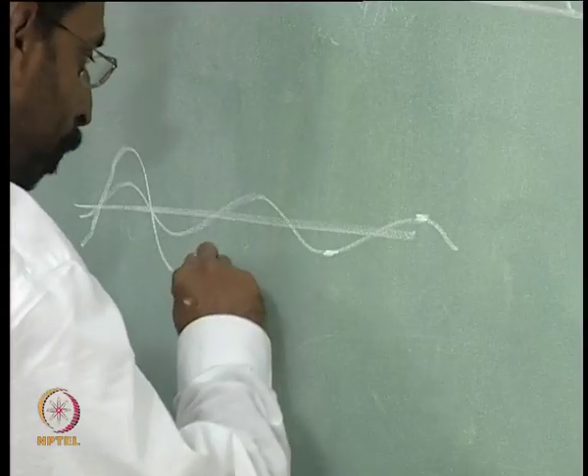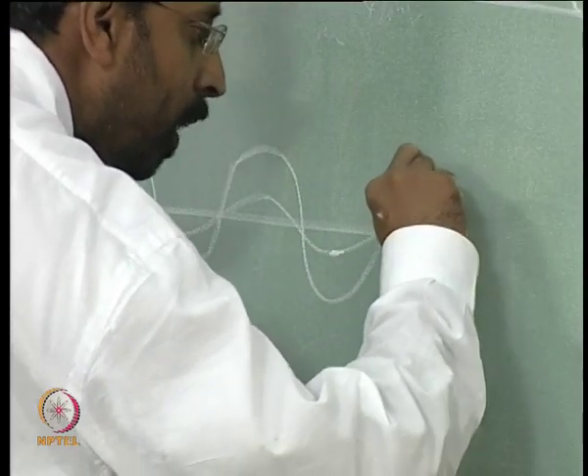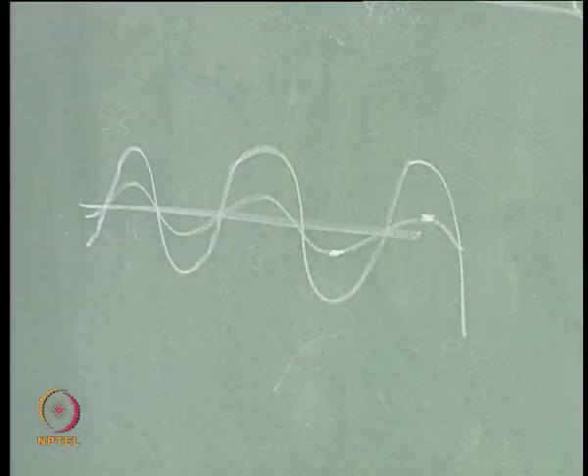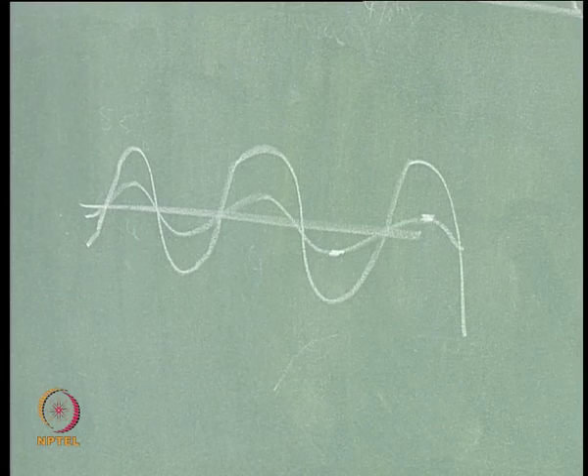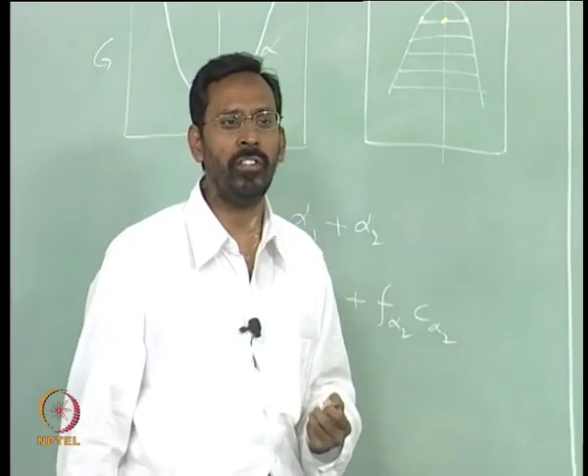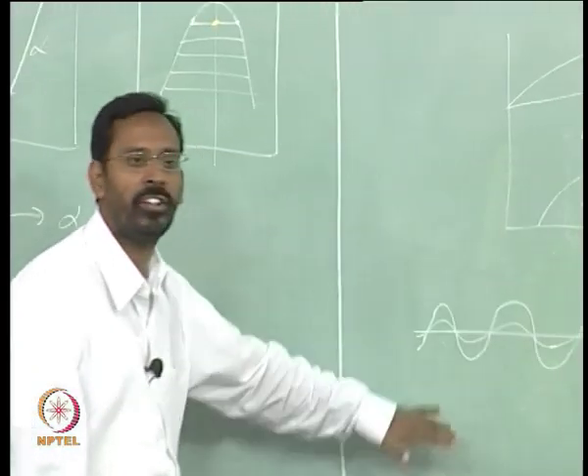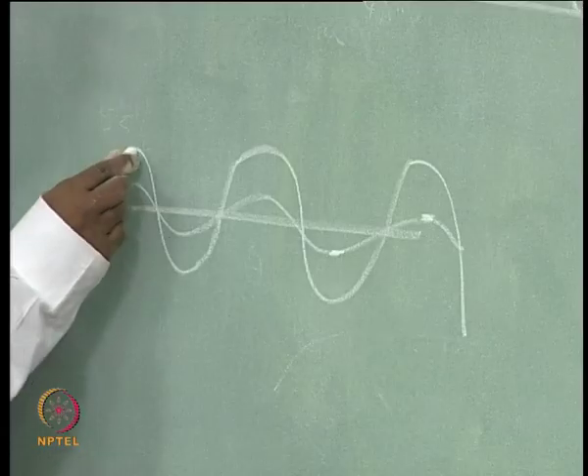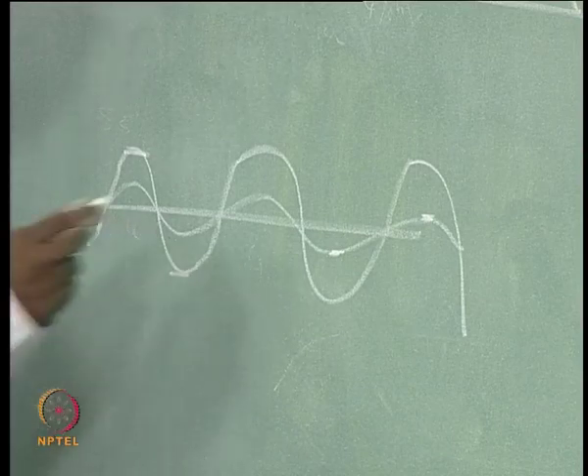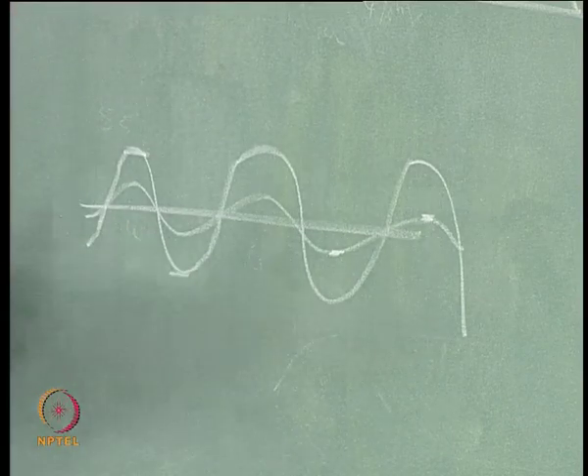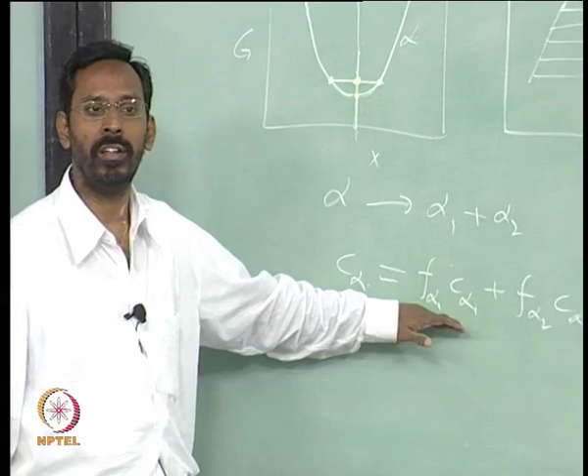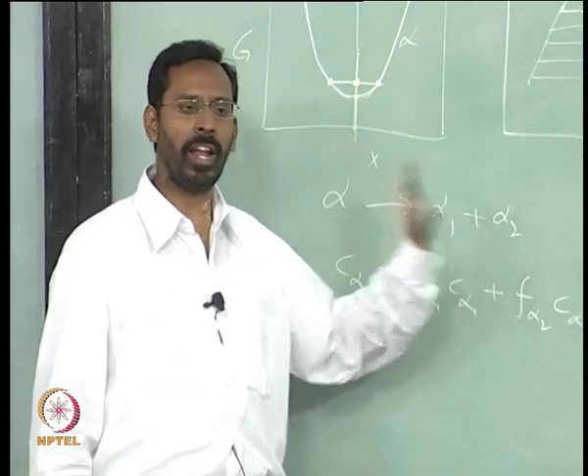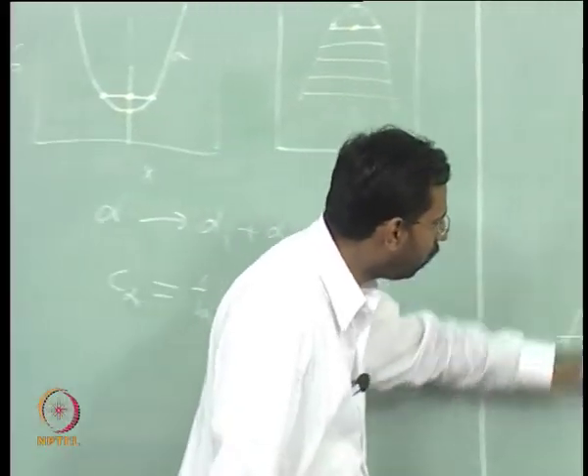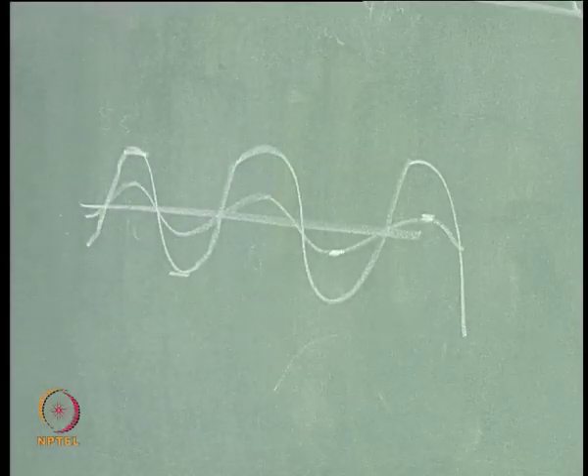So this fluctuation starts with the same wavelength. The wavelength gets fixed, which may be of the order of a few nanometers, and within that wavelength the amplitude starts changing. That means this region becomes richer in copper, this region becomes less rich in copper, but the overall composition satisfies this. The overall composition of the alloy is the same, but you will see that these compositions start increasing and decreasing, and to an extent